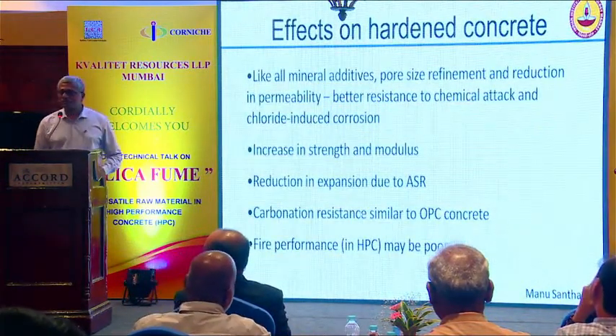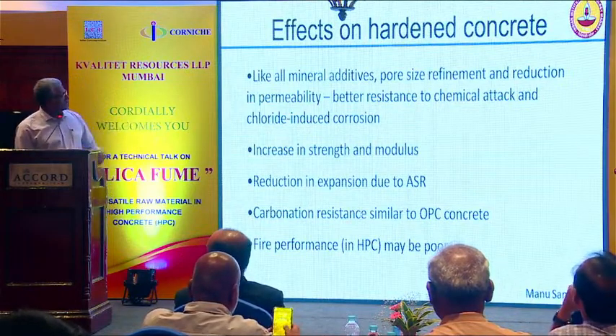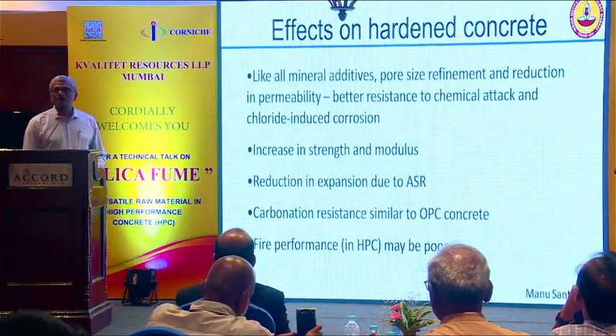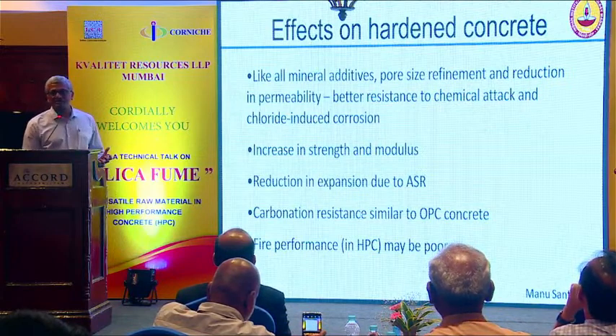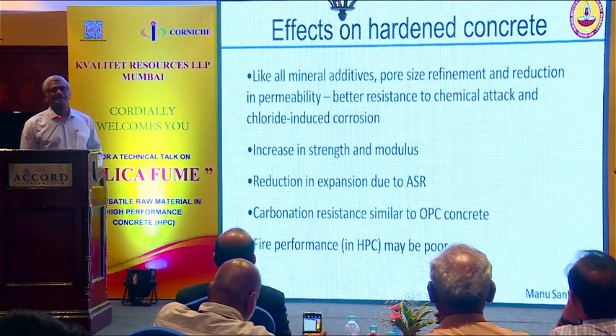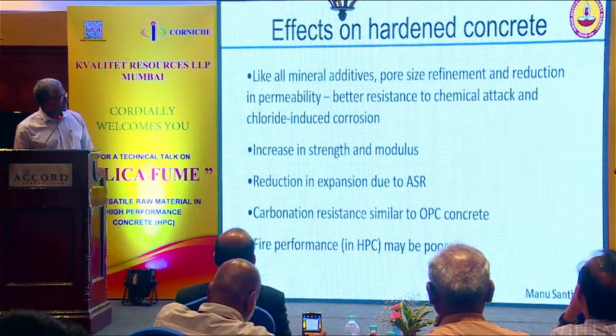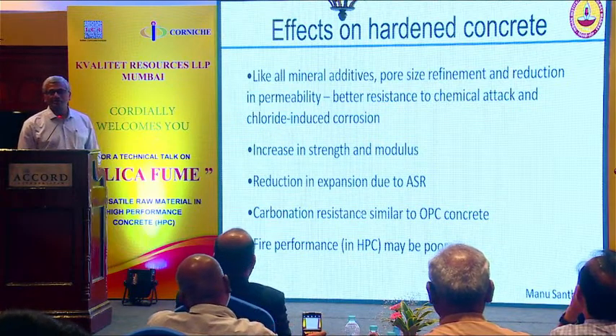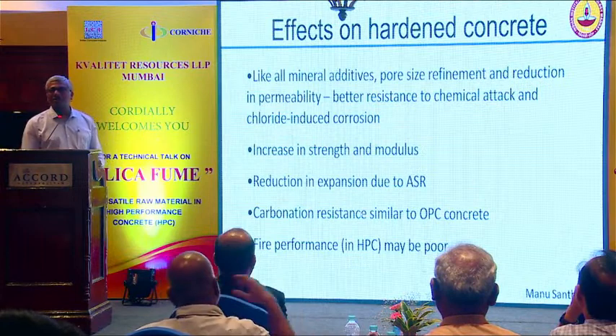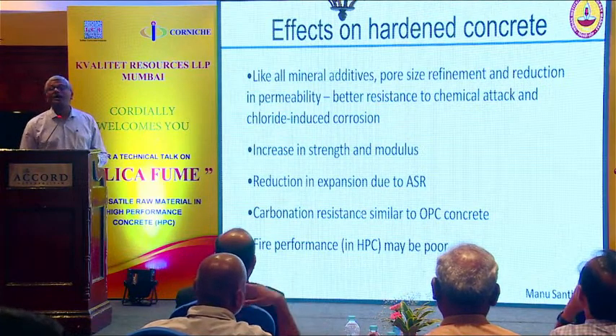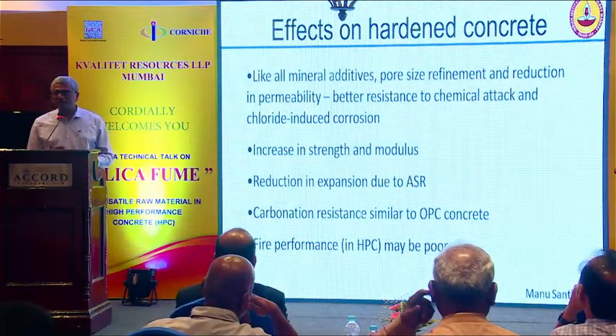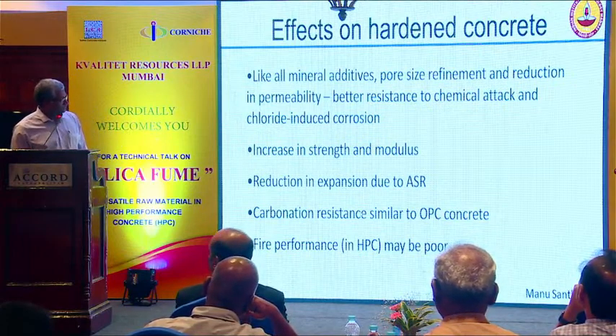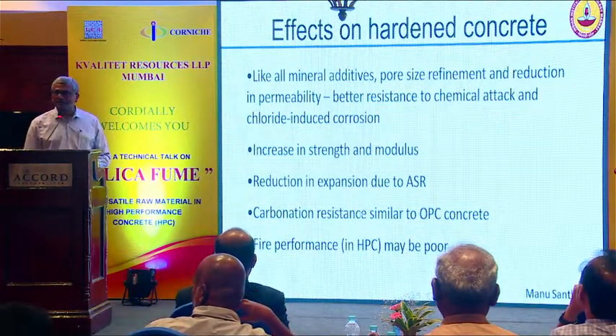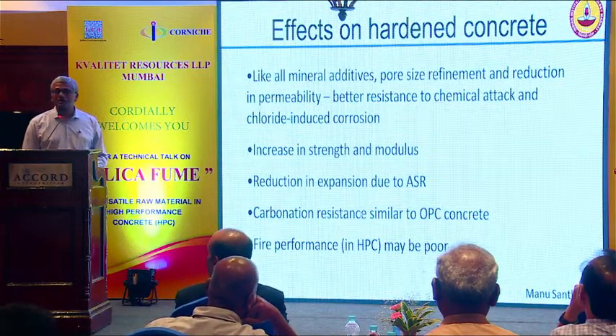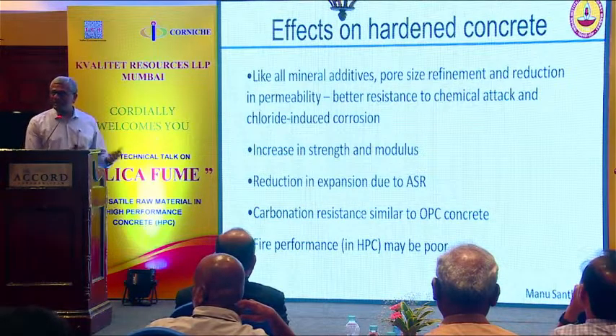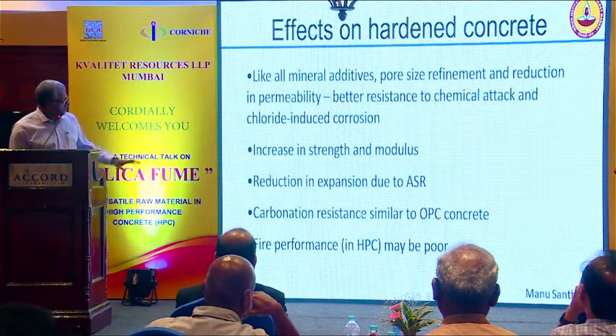Now, hardened concrete, of course, if you've done your concreting well, like all mineral additives, silica fume obviously will give you an additional kick because of its extremely high fineness and its high reactivity. So you get pore size refinement and reduction in permeability, and that's what is the basis of putting silica fume for all your high performance concrete. For high performance concrete, you have to go with silica fume. You get better resistance to chemical attack, improved resistance to chloride-induced corrosion. Silica fume definitely helps in all of these environments.